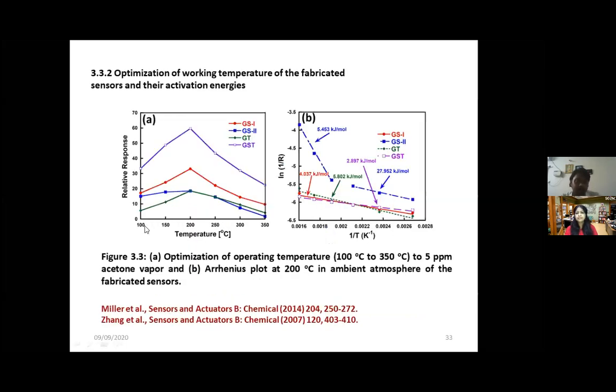And as we have seen, this operates at elevated temperature. We wanted to ensure at what temperature we observe a maximum response here. So we varied from 100 to 350 degrees Celsius, and we infused 5 ppm of acetone vapor to check the response. And we found that 200 degrees Celsius is the most sensitive for all four sensors. This is the Arrhenius plot. Arrhenius plot is the rate of change of resistance with respect to temperature in Kelvin.